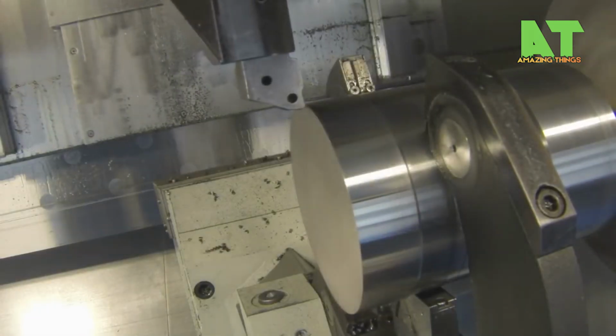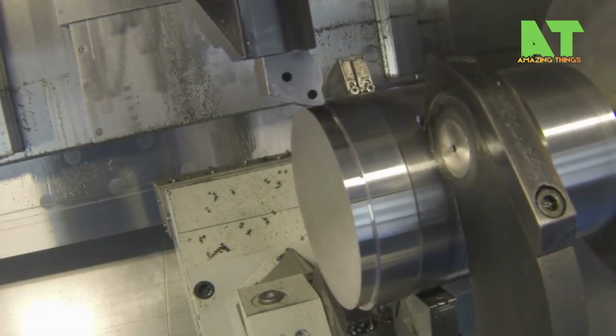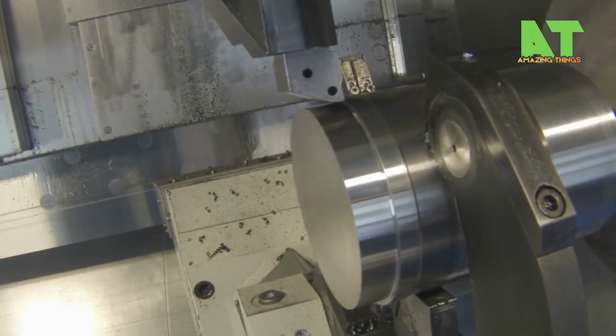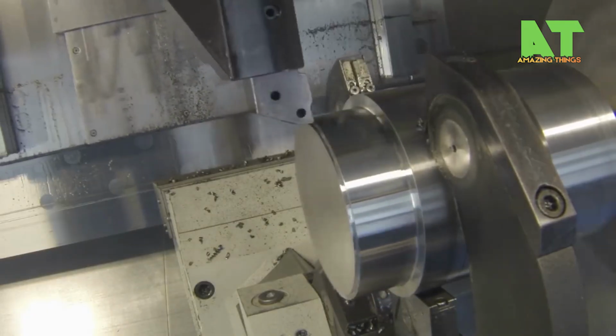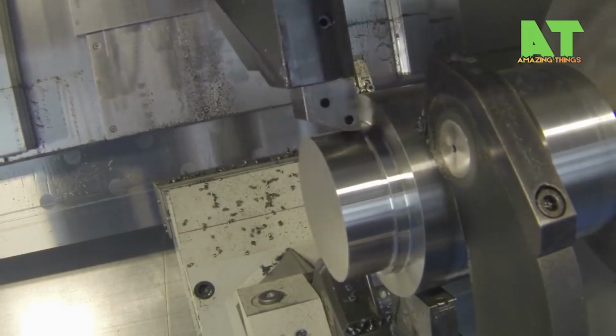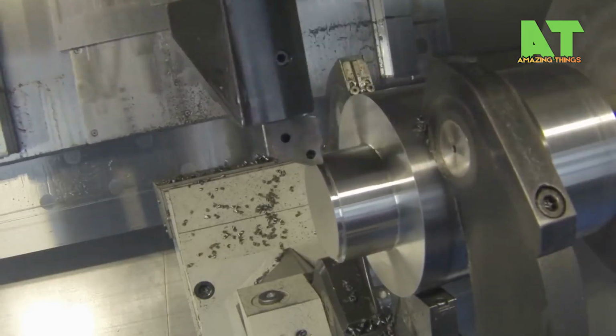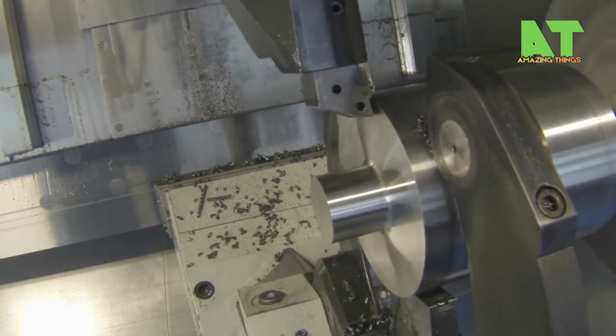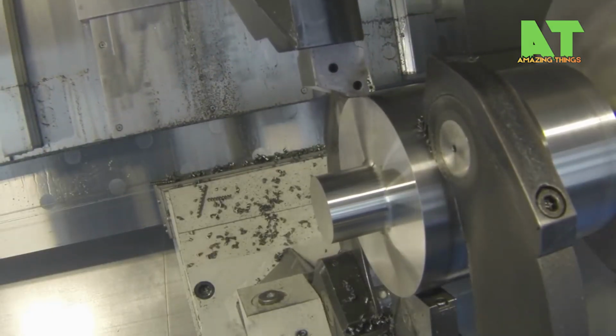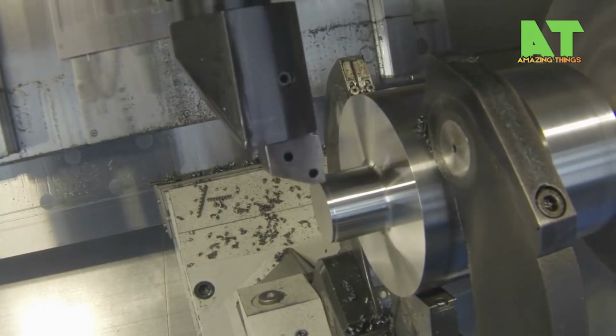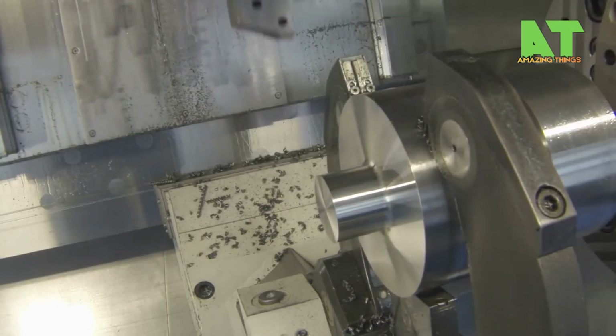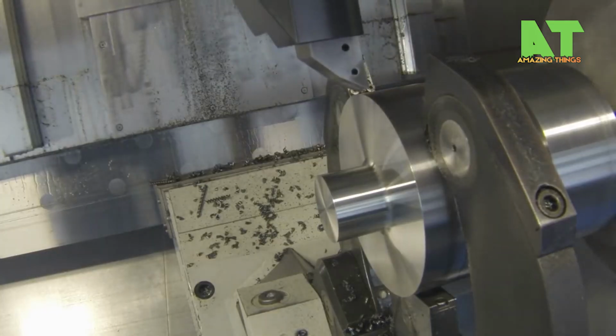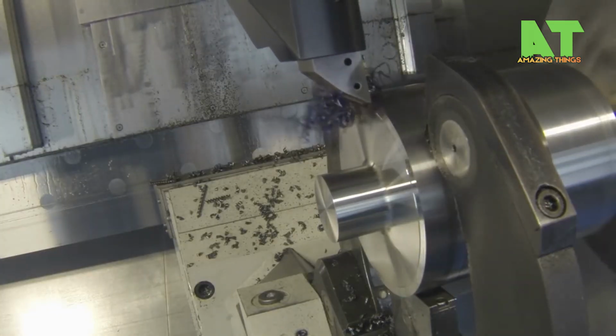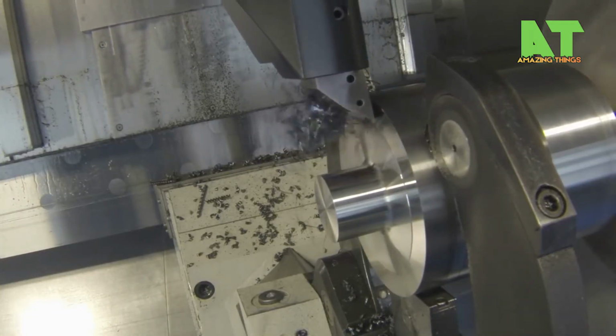Now comes the most critical phase: finished turning and grinding. The journals are finished turned to within a few microns of their final size, then handed off to precision cylindrical grinding for the final surface finish. Finally, the crankshaft goes through CMM inspection. A coordinate measuring machine sweeps across every critical dimension, verifying journal diameters, roundness, straightness, and the angular relationship between each pin journal.